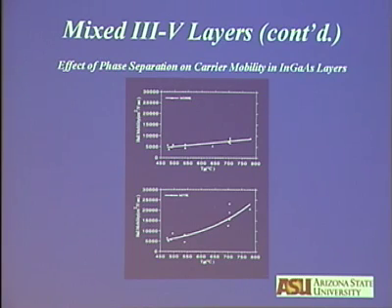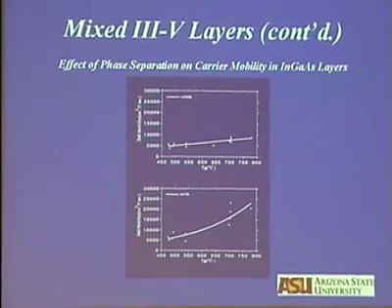Indium-rich regions have a lower band gap. People have demonstrated that, so it's acceptable. And the gallium-rich regions have a higher band gap. In equilibrium, the carriers would like to stay in the low band gap regions. When you apply a field to measure mobility, the carriers have to overcome the barrier between the low band gap region and the high band gap, micro barriers. And that's how we explain a reduction in carrier mobility in the presence of phase separation.